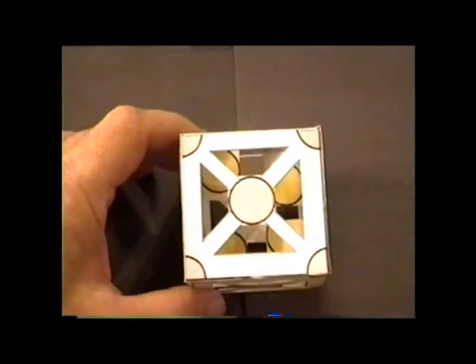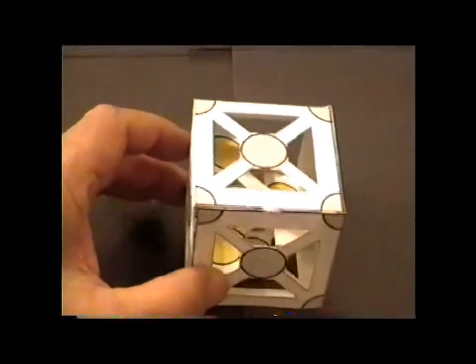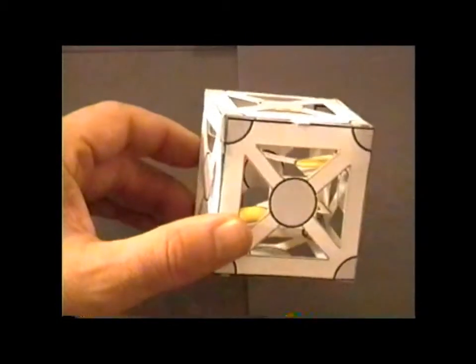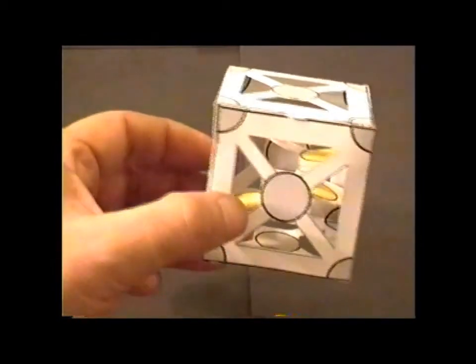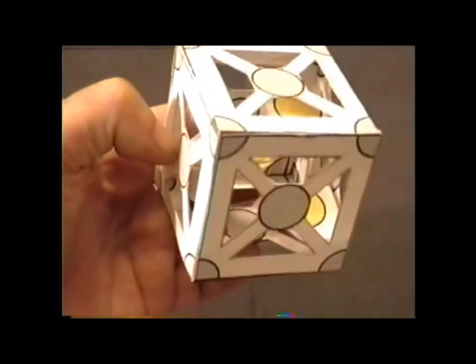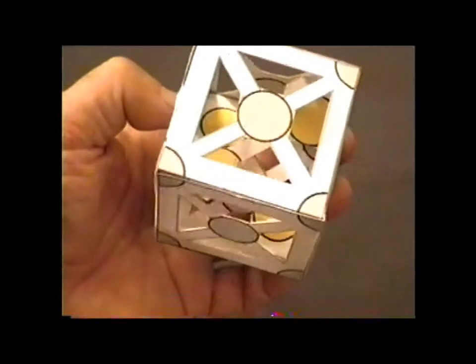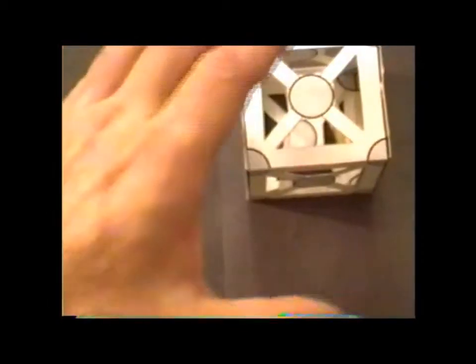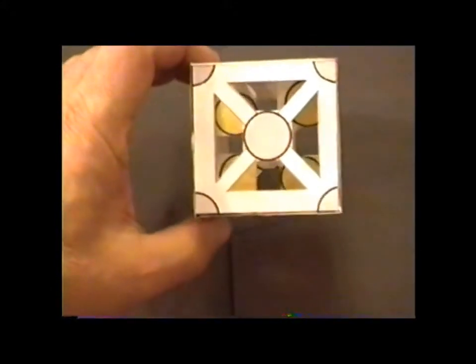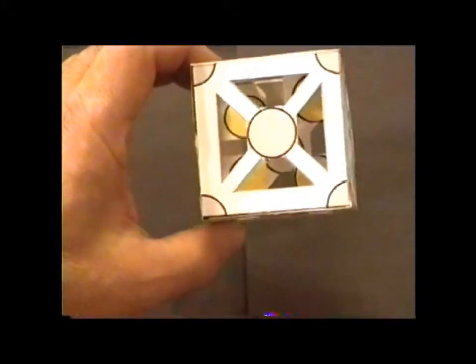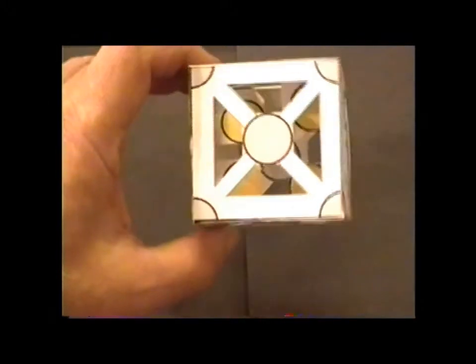If we look at it this way, we can get a better three-dimensional appreciation for where the sulfur atoms are located within the lattice relative to the zinc atoms. So this is exactly the same as diamond if both the zinc and the sulfur atoms were each replaced identically with carbon.